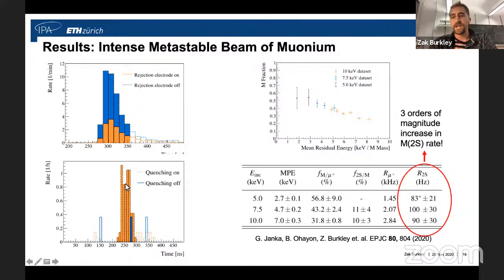And then we wanted to measure how much of this was in the 2s state. So this graph on the bottom left is the quenching on and the quenching off. So with the quenching on, we should look for Lyman alpha counts. Here in the orange, we see them. And with quenching off, we shouldn't see any Lyman alpha. And indeed, we didn't see any definite signals of Lyman alpha in this specific time window.